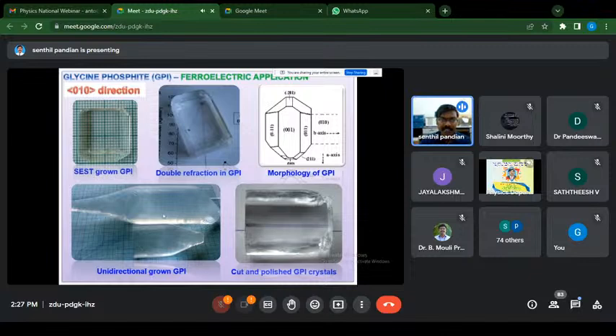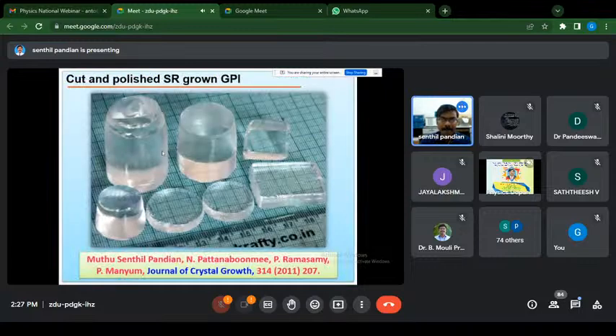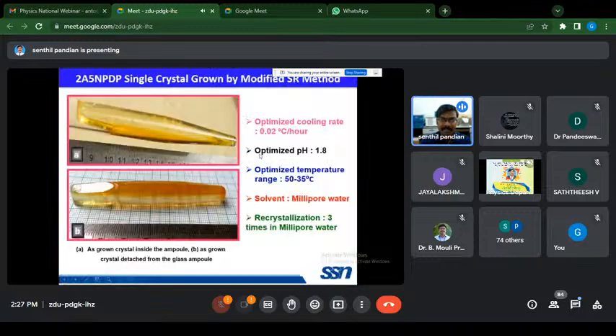This is the ferroelectric glycine phosphite single crystal. This is the conventional method grown crystal. This is the as grown crystal grown by the SR method. This is the double refraction pattern. We have selected this polar b direction, and this is the cut and polished wafer of this glycine phosphite, and this is the 2-amino-5-nitropyridinium dihydrogen phosphate single crystal grown by this SR method.